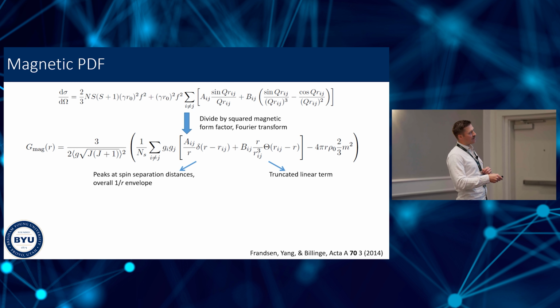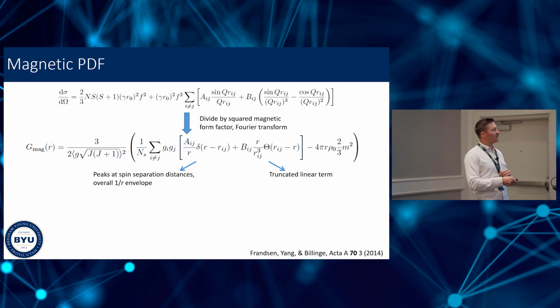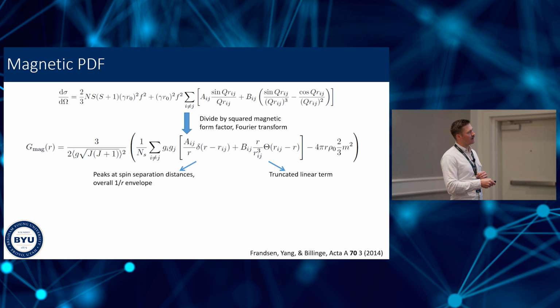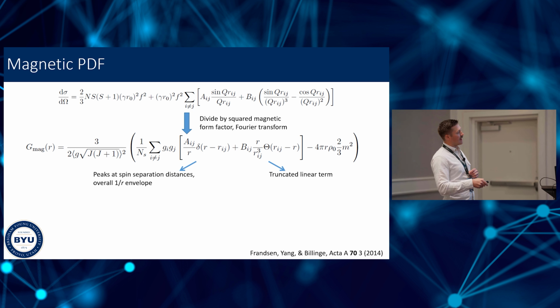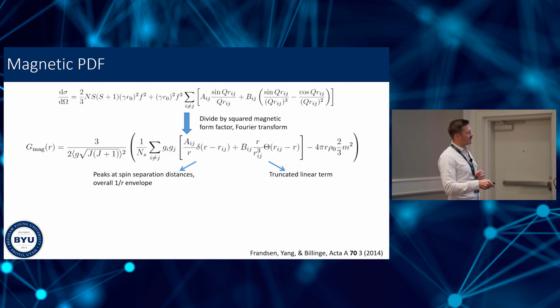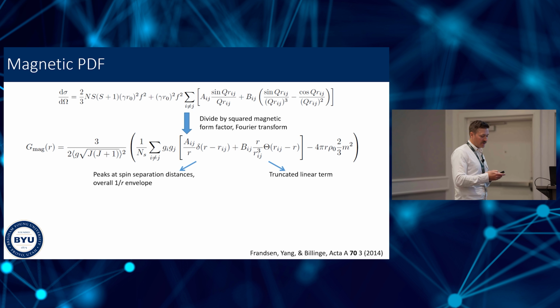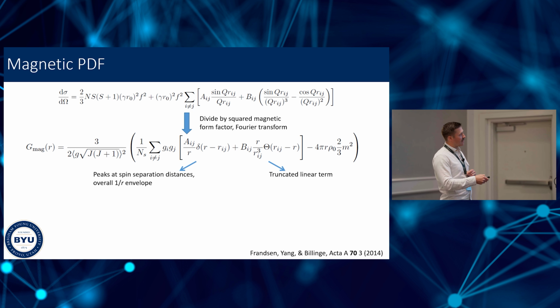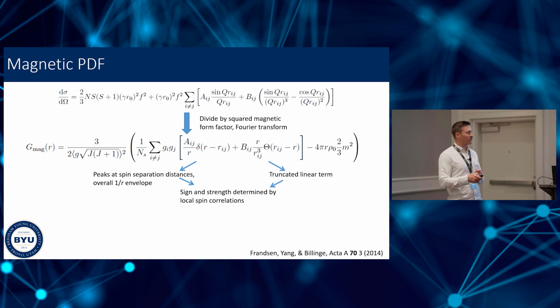It also, and this is very similar to what we get in atomic PDF, has a term that's linear in R. This is kind of a strange term. It's linear in R, and then it actually turns off at distances beyond the spin pair separation distance. So this is not in atomic PDF. This is something new. And then there's this additional baseline term which is related to the average net magnetization of your material. But anyway, these features here, the peak and the baseline slope, their sign and strength are determined by the local spin correlations, which are encoded by these coefficients A and B.